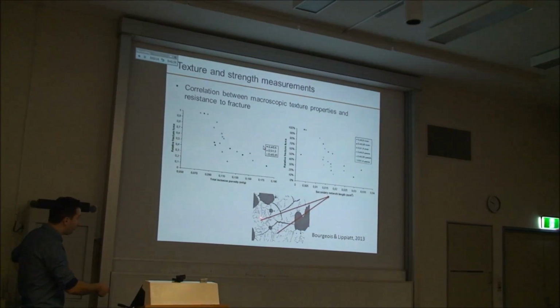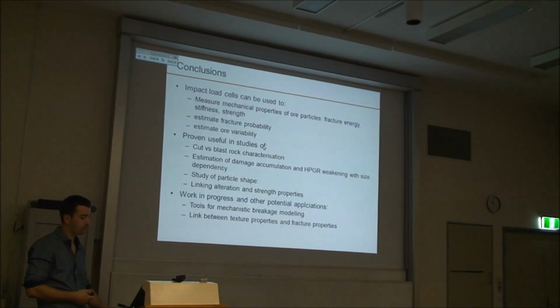So this is in meters of crack per square meter. If that is, let's say, 1 square meter, how much length of those cracks is in the particles, and they related that to the reduction in the fracture force. So basically what this says is that the more secondary fracture, like those little ones you have in the matrix, the softer the product. And this can be assessed with impact loads. And so this is really a space to watch, and there is a student starting here, who is going to get these kinds of properties in a PhD work, so just keep an eye on that in the near future.